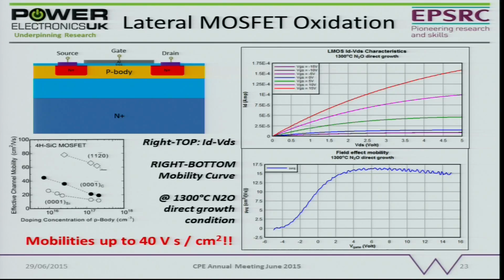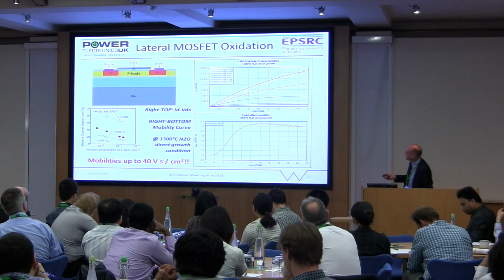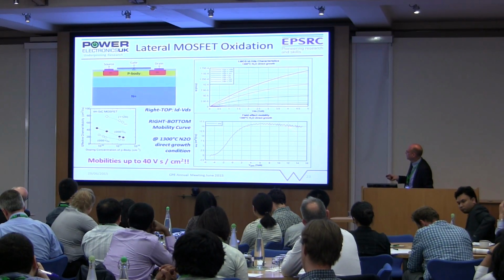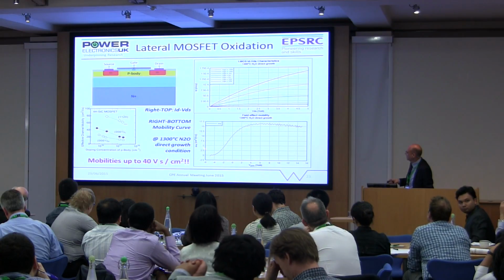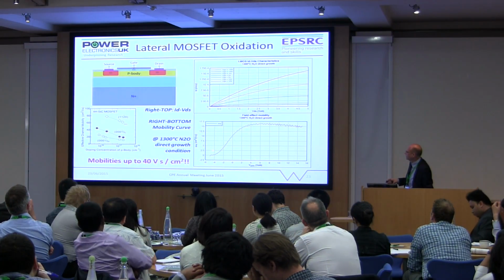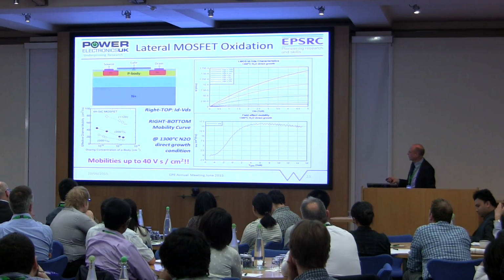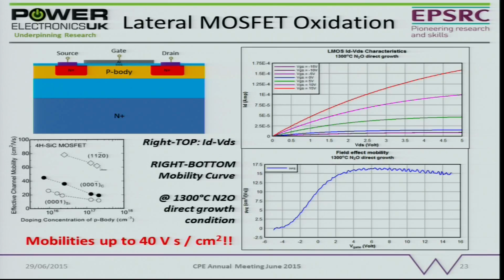We've also done some work on some lateral MOSFETs on these structures, on the EPIs that we've grown, and you can see that we've got some mobilities which are about 20. Typically, this is using some post-oxidation anneal process. Typically, when you grow these oxide layers on silicon carbide without doing some processing, you get mobilities of down here. So this is like 4 or 5 times better. We've actually improved this quite considerably now. We've got up to 40 now, so it's on a different scale.